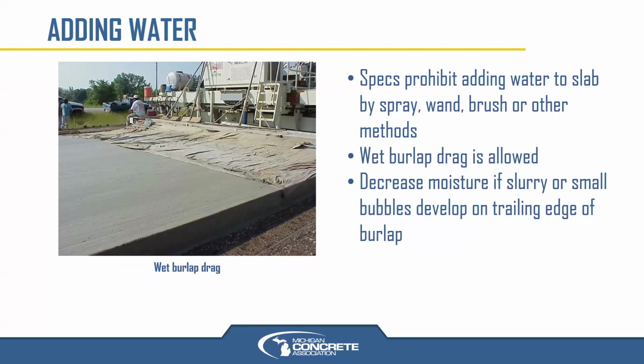Speaking of adding water, most specifications, again, if you're working on a job that has specifications and inspection and everything else, prohibit adding water to the slab by spraying with a wand, brush, or other methods. You are often allowed to do a wet burlap drag if necessary. A lot of the paving contractor side of the industry will typically have a machine that has that mounted on it, and they try to keep that burlap wet. They'll spray it, make sure it maintains its moisture, so it's not pulling water out of the surface or creating bubbles as it's being dragged. So that is a way to get water on the surface at an even amount, or at least keep the surface moist before the next finishing operation.